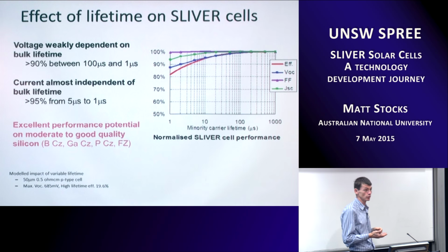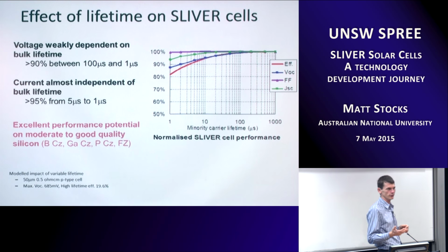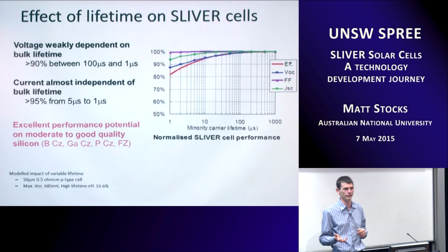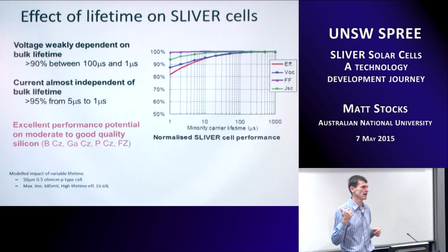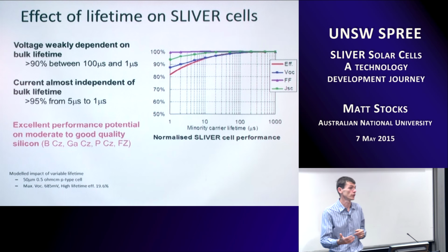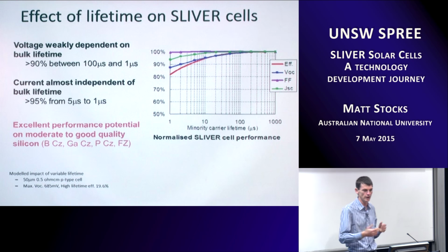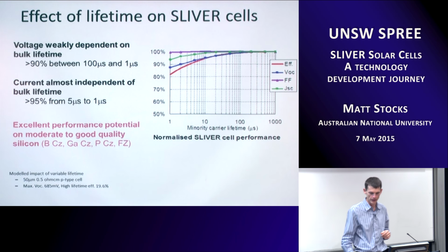We're quite robust to material quality. So we started off with float zone material, because float zone material's easy. We started off with that at the ANU, and when we transitioned to the facility in Regency Park, we made the move from 4-inch to 6-inch because bigger wafers are more economic, in particular around the processing side of things. But we stuck with float zone to begin with. But then we managed to make the transition to CZ as well without having too big an impact.